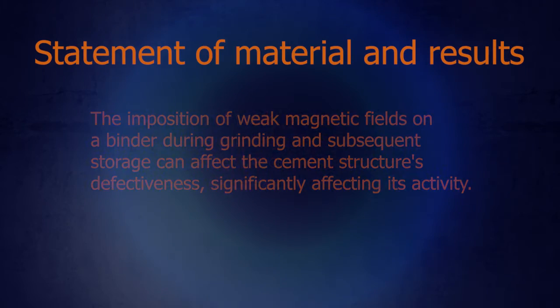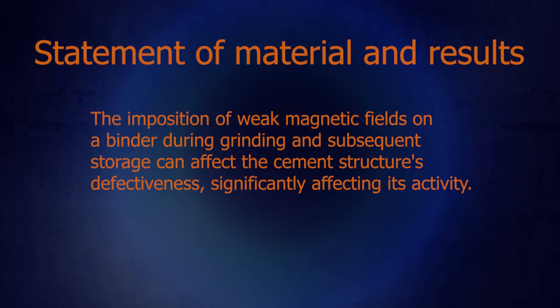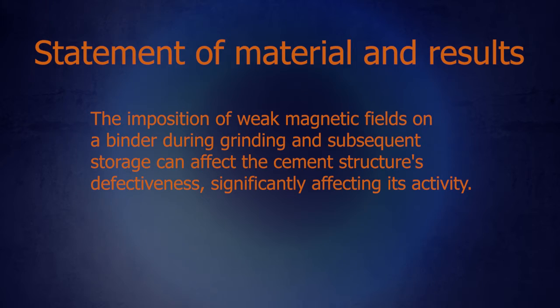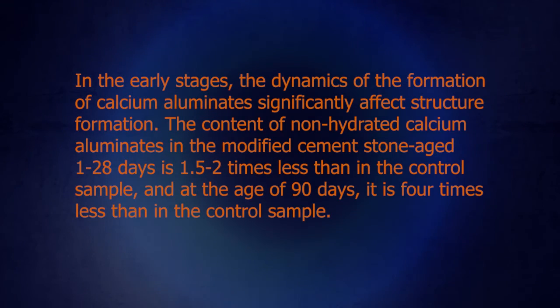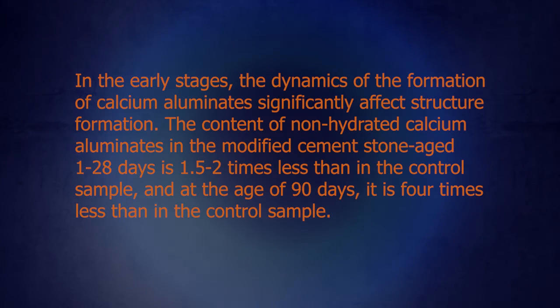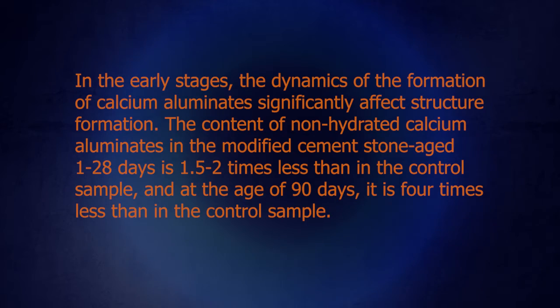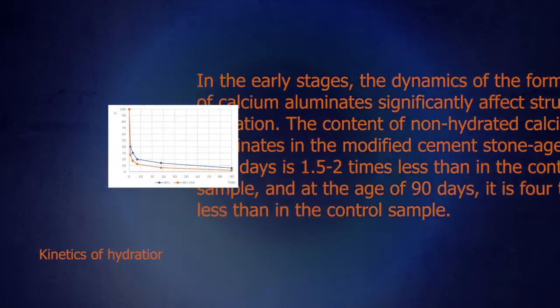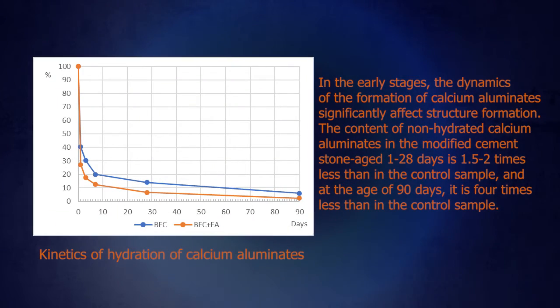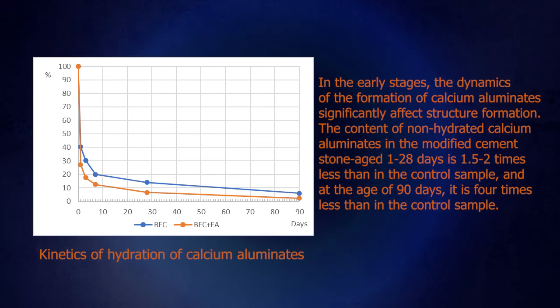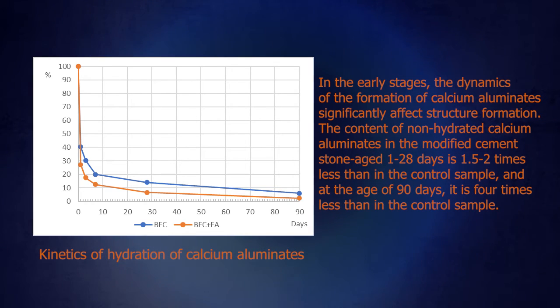The imposition of weak magnetic fields on a binder during grinding and subsequent storage can affect the cement structure defectiveness, significantly affecting its activity. In the early stages, the dynamics of the formation of calcium aluminates significantly affects structure formation. The content of non-hydrated calcium aluminates in the modified cement stone aged 1 to 28 days is 1.5 to 2 times less than in the controlled sample, and at the age of 90 days, it is 4 times less than in the controlled sample.